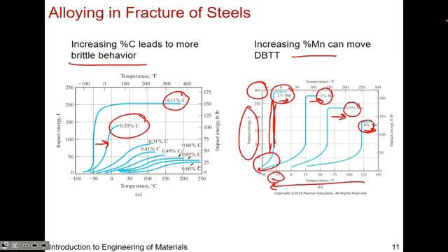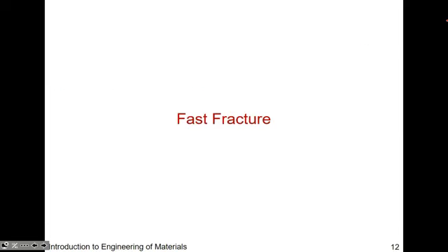As temperature increases, what was the second part of your question? The impact energy change, right. So it depends on the temperature, and by the temperature you mean the ductile to brittle transition temperature, or DBTT, right. So yes, above that temperature, for a certain composition of manganese in steel, it does change. Your impact energy is much higher in the ductile region than it is in the brittle region. Okay.